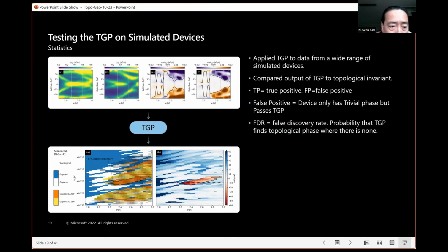Oh, question. So zero bias peak can still be protected around the gapless environment? Well, yeah, so the zero bias peak, there's no gap, so there's no reason for it to be protected, but there can be accidentally, there can be zero bias peaks, and sometimes they're stable. I mean, that's what this yellow region over here is showing. What is probably happening is in those regions, the gap may not be quite zero, it may just be small, and we can't resolve small from zero.